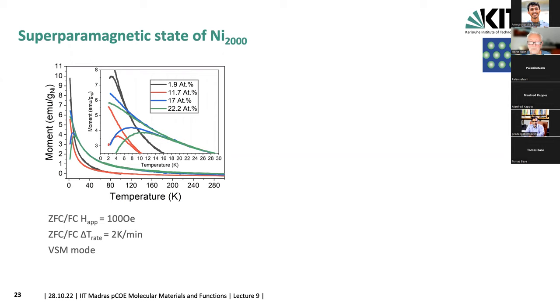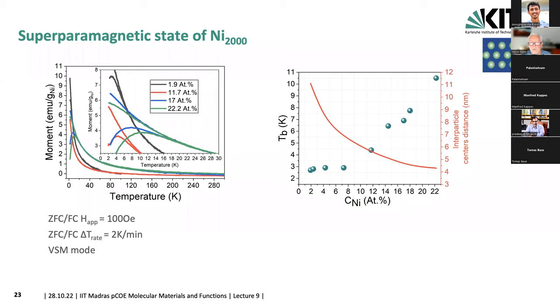And this you follow by this approach, which is standard in SQUID measurements in this VSM vibrating sample mode, that you do zero field cooling measurements. And from that, you can determine the blocking temperature, which is shown here as green dots. So TB is the blocking temperature. And you see that for a large range of the nickel concentration, basically from 2 to almost 10%, where there is no data point, but at least to 8%, there is no change of the blocking temperature as a function of the nickel concentration. So there are more and more clusters, because the cluster size is fixed by our synthesis parameters. There's no change in cluster size, but there is a change of the distance. They become closer and closer as you go to higher nickel concentration, but they're still not interacting.